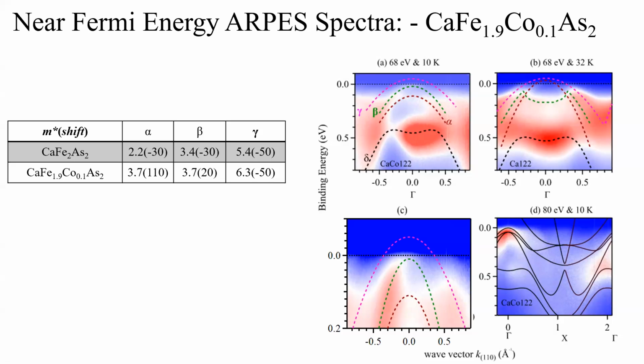Okay, so there are many different kinds of bands here. So are these bands within the superconducting energy gap, or what are the different energy scales here? Since your sample is superconducting, there will be an overall superconducting energy gap. Also, due to interactions, there are many gaps, but the gap will appear at even lower temperature. So it's not at 10 Kelvin. The gap will appear below, I guess, 8 or 9 Kelvin. At this point the sample is non-superconducting. And also the gap value is very small. Usually these gap values are of the order of, if the transition was say 20 Kelvin, and I'm measuring at say 15 or 10 Kelvin, then the gap value will be of the order of say 5 or 6 meV. So it's very difficult to see from here.